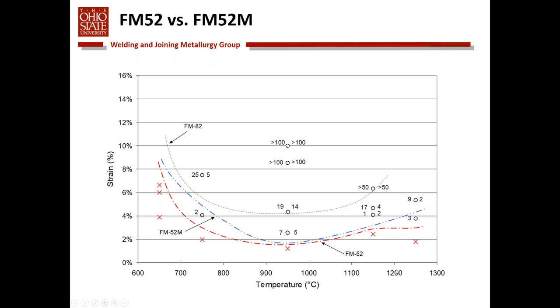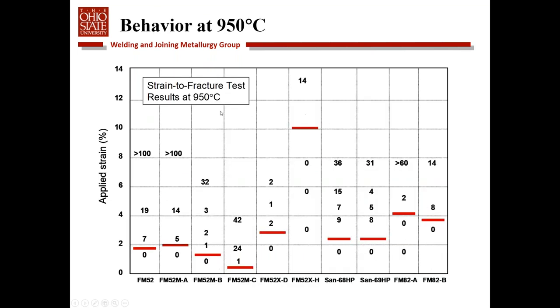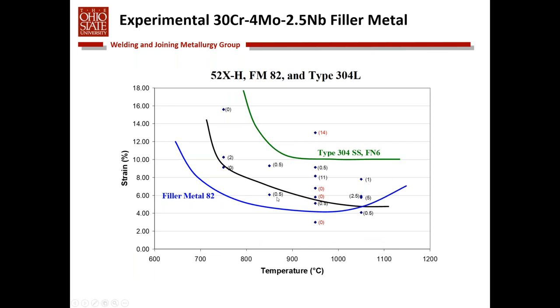The one thing that we noticed early on, which is sort of interesting, is that for most stainless steels and nickel base alloys, the low point in these curves is around 950 degrees centigrade. So we started asking ourselves, well, why run all these extra tests out at the low and high extremes? Why don't we just pick 950 degrees C? What we show here, for a variety of nickel-based filler metals, is that the red line indicates the threshold strain for cracking to occur. The numbers here represent the number of cracks, and we can simply test a dozen samples or fewer at 950 degrees C to basically get that result. Here's some additional data for some different filler materials. Filler metal 82 is somewhat resistant to DDC. You see its minimum strain is about 4%.